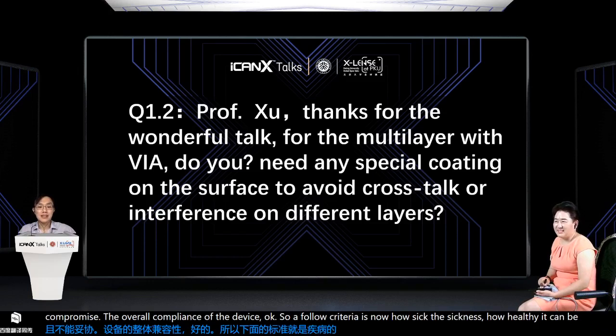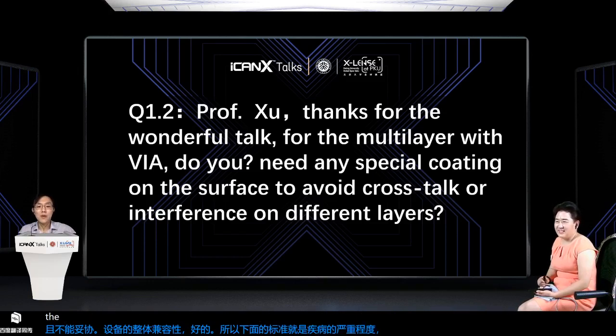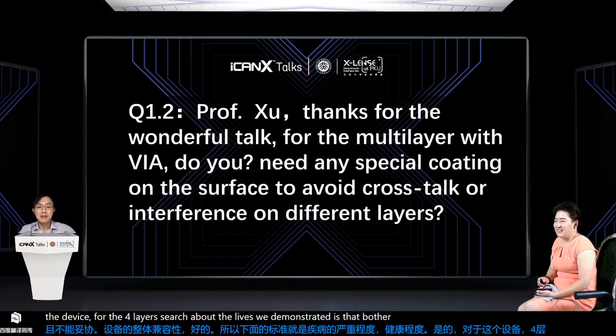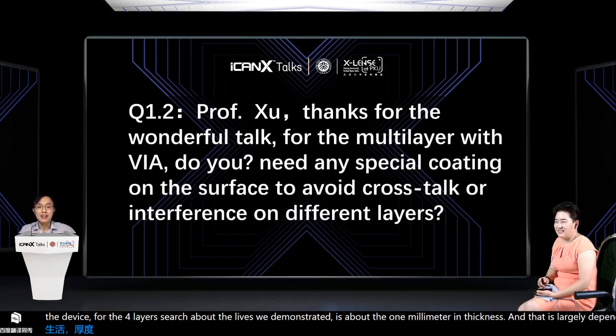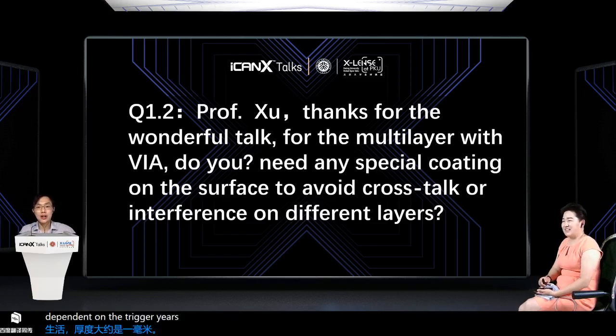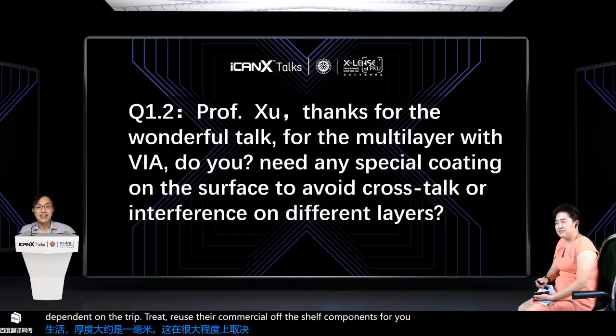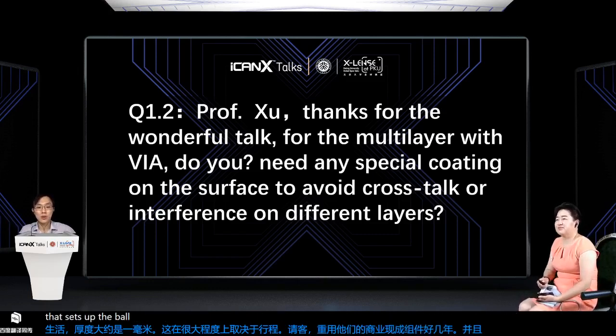Okay, so a follow-up question is, how thin can it be till now? Well, for the 4-layered stretchable device we demonstrated, it is about 1 millimeter in thickness. That is largely dependent on the commercial off-the-shelf components we use. The thickest is 1 millimeter. So that sets the bar for the overall thickness of the device.